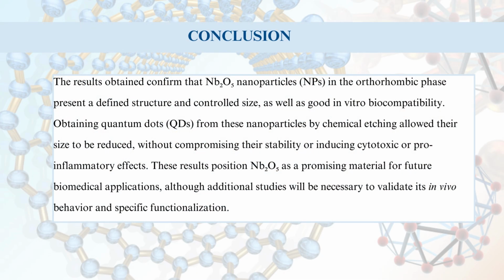The results obtained confirm that niobium pentoxide nanoparticles in the orthorhombic phase present a defined structure and controlled size, as well as good in vitro biocompatibility. Obtaining quantum dots from these nanoparticles by chemical etching allowed their size to be reduced, without compromising their stability or inducing cytotoxic or pro-inflammatory effects. These results position niobium pentoxide as a promising material for future biomedical applications, although additional studies will be necessary to validate its in vivo behavior and specific functionalization.